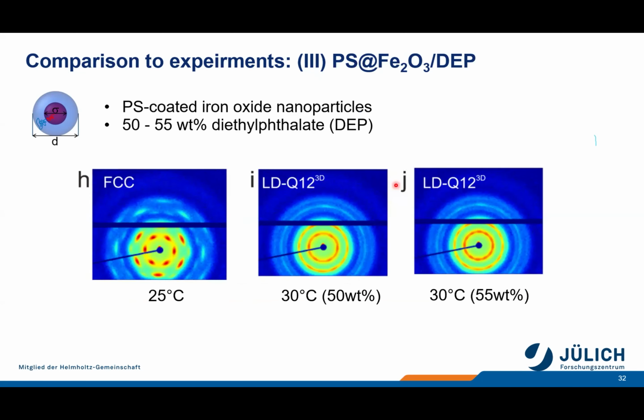Then the people come and tell you, oh, you have the aggregation number and this could be non-constant if you increase the concentration or change the temperature. And this might be some reason why you have these things appearing. So we started using nanoparticles. These are iron oxide nanoparticles, and they are coated with polystyrene. And in this way, we assure that the core size is always the same, and also the shell size is always the same.